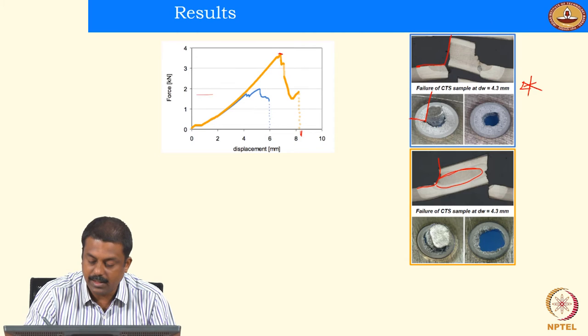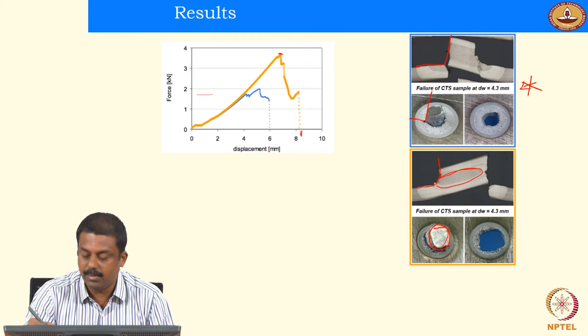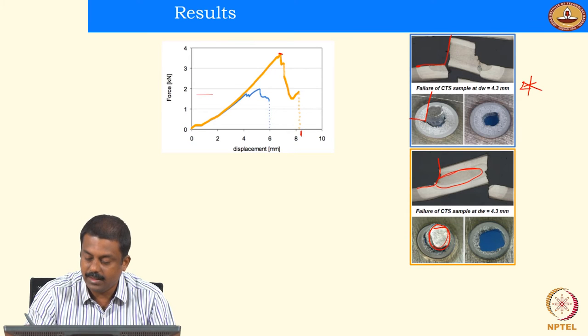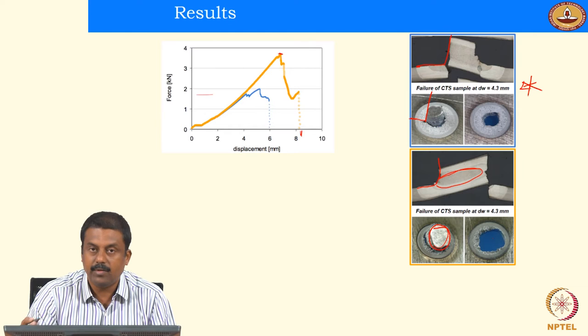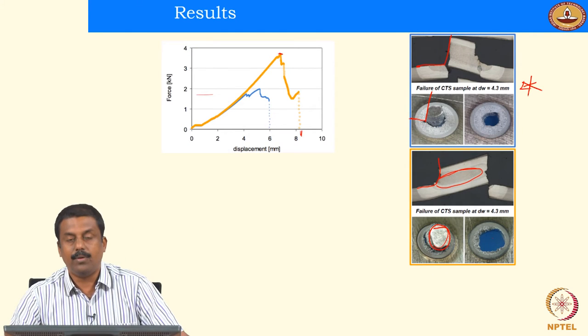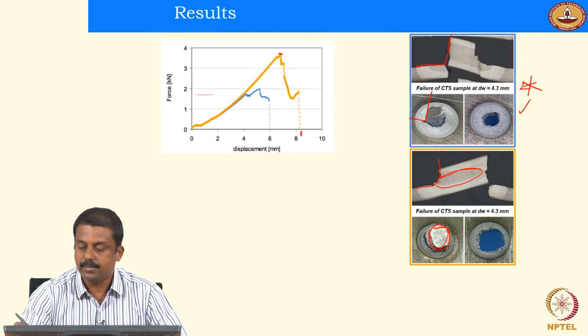Okay, and then second pulsing increased the plug size as well. So you increased significantly the plug size. The plug is intact. You see that the plug has come out intact. Almost 80% of the plug is intact. That means that it is a much more acceptable failure mode compared to the single pulsing case.